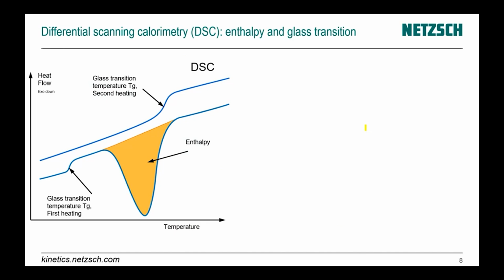Differential scanning calorimetry can also provide very good information about the enthalpy of our curve as a peak area, and a glass transition where we have a change of CP and a step on the CP curve. We know that the glass transition temperature before curing has a lower value than the glass transition temperature after curing. For example, for the second heating, we have a glass transition which is above the glass transition temperature for uncured material. This is DSC.